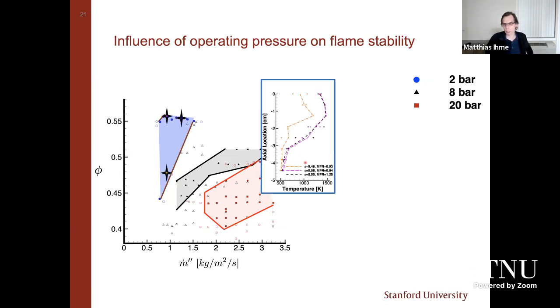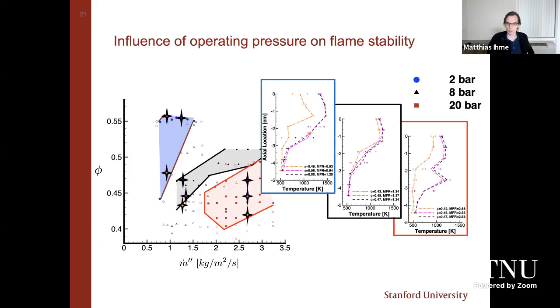If you look at temperature profiles through the burner, I'm plotting here the axial locations through the burner. At the top is the exit of the burner, and then we're moving down. You're seeing that we have a rather broad flame zone. The temperature is fairly homogeneous at these conditions. And if you look at different temperature regimes, you're seeing that at some point the flame detaches and pushes a little bit further downstream, but overall there's a very good representation of the flame profile, and we have a rather nice and stable temperature field inside this burner.